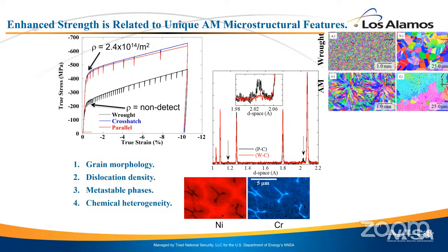And there's chemical segregation in the AM material. Because you go through the solidification so fast, the atoms don't get to go where they want to be. What I'm showing you here is nickel and chromium content. You actually see high points of chromium, and that's where the ferrite is. Chromium stabilizes the ferrite. So where you have high points of chromium, you have ferrite.